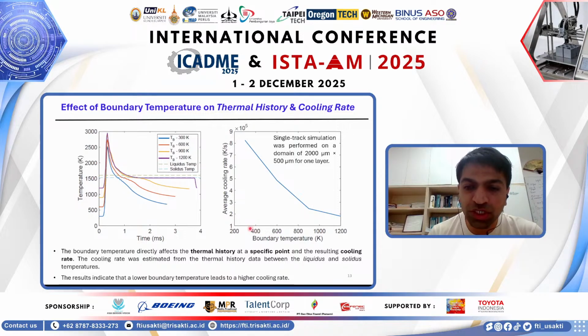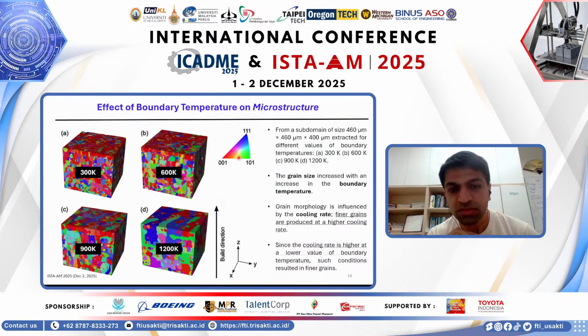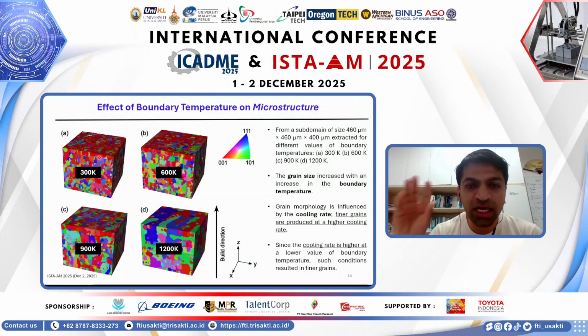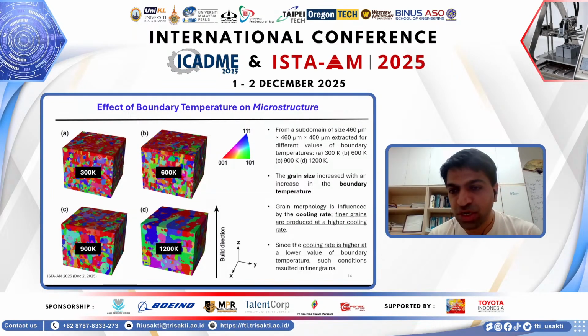While if the boundary temperature is much lower, it means that the cooling rate is higher, which means that it is likely that your grains are going to be much smaller in size in your entire microstructure. And these grain sizes will then have an impact on the mechanical property of the 3D printed device as well. So here are 4 grain structure maps you can see for 4 different temperatures, ranging from 300 Kelvin to 1200 Kelvin. And you can clearly see that the grains are much bigger in size for the higher temperatures, while they are much smaller and equal in size for the smaller temperature simulation results.